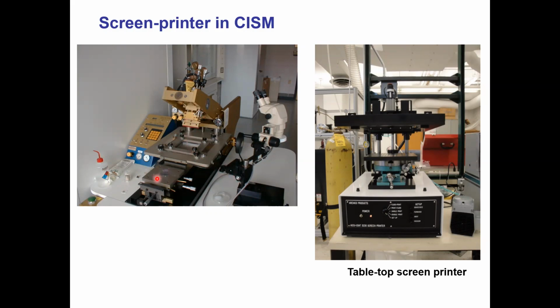automatically, and then your sample substrate will be sitting here that can be pushed. So in that case, your substrate will be just underneath the screen, and you can adjust the snap off distance, the Z direction distance, and XY positioning, and you can look under microscope to see the alignment of the substrate for screen printing. Or you can buy a tabletop screen printer, something like this, less expensive than that, but you can sort of control the squeegee pressure and ink deposition and etc. by nitrogen pressure from a nitrogen cylinder. So it's not as sophisticated as the other one, but it works pretty well.